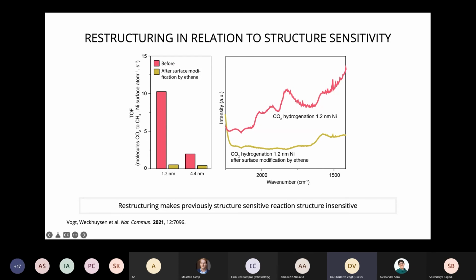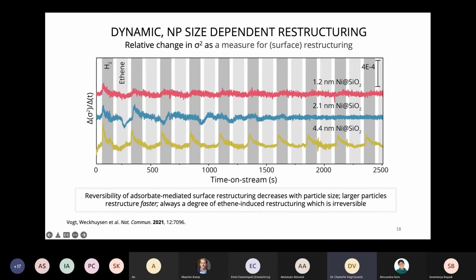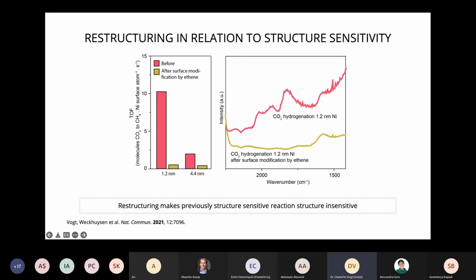So we took that hypothesis and we wanted to test that both with activity and with spectroscopy. So we took different sizes of nickel nanoparticles. We flowed ethene over the surface, restructured the surface, and then cleaned it. So first purged nitrogen and purged hydrogen, which means that only this irreversible amount of restructuring should still be there. And then we did a structure sensitive reaction. We measured the activity of CO2 hydrogenation before and after restructuring.